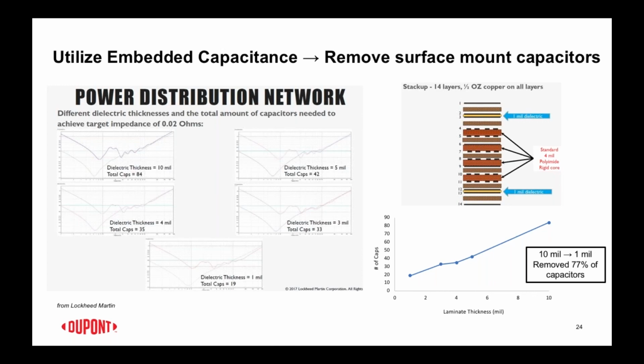It's not truly a linear relationship, but it's kind of close. The 10 mil gap happens many times when people put their power plane and the ground plane and they put the signals in between, and that's not a good way for power distribution to run. You really want your power and ground planes to be next to each other to get the optimal power distribution network. And so by going from 10 mils to 1 mil, you can remove 77% of the decoupling capacitors.